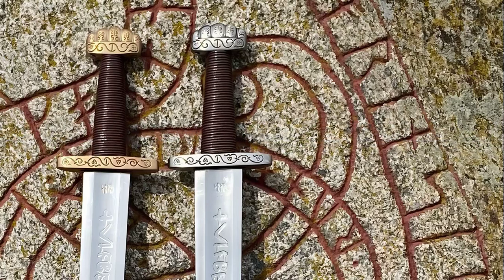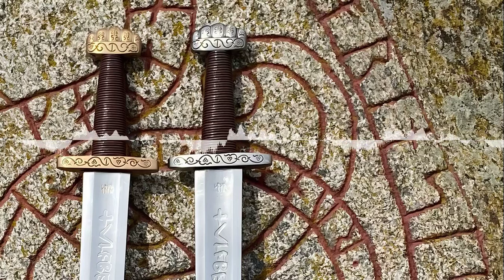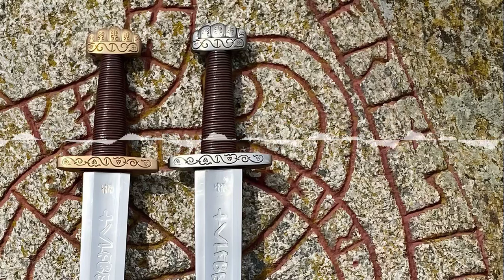But against thrusts? With most swords, no problem for the armor. They simply couldn't get through riveted mail. But the Ulfbert had this needle point. It could slip between the rings. And then what? Tests with replicas have shown that the needle point could damage the rings on a targeted thrust. Some were burst at the rivet, others were cut through or bent.